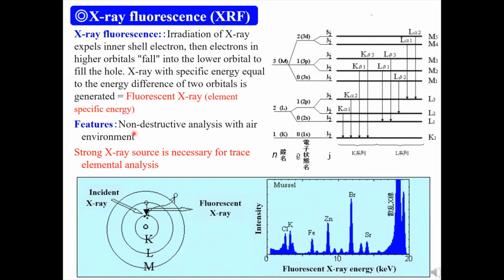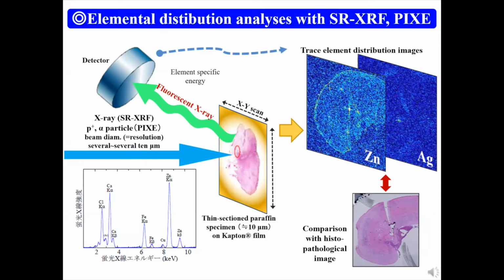However, the sensitivity of XRF with a laboratory X-ray source is not enough for the analysis of trace elements contained in tissues. But extremely bright X-ray, synchrotron radiation X-ray irradiation, makes it possible to detect the trace elements. In this study and the following studies, microfocused synchrotron radiation X-ray was irradiated on the thin-section tissue specimen and generated fluorescent X-rays were detected. With two-dimensional scanning of the specimen, the elemental distribution images could be visualized. In comparison with the pathological images, the relationship between the trace elements and tissue degeneration can be revealed.